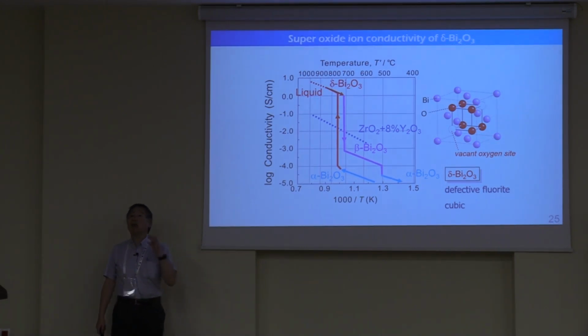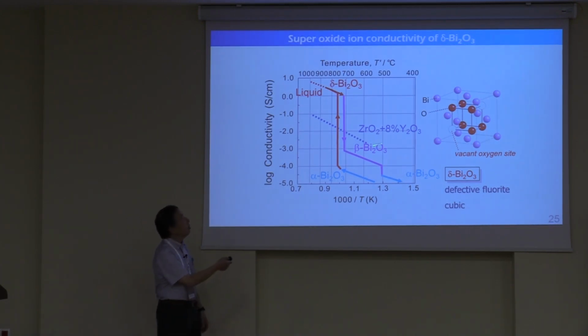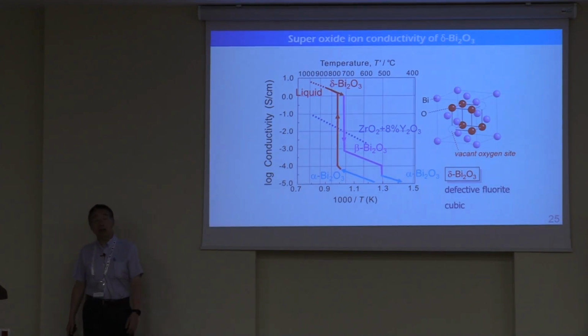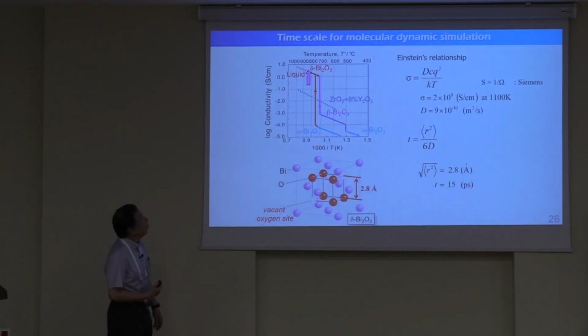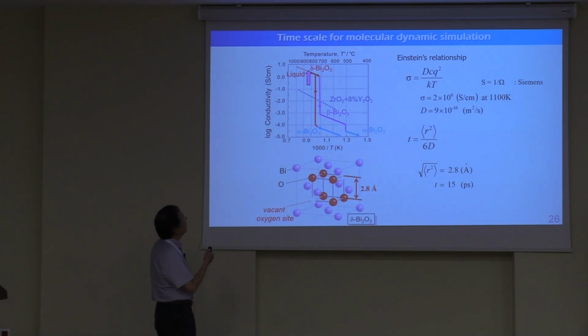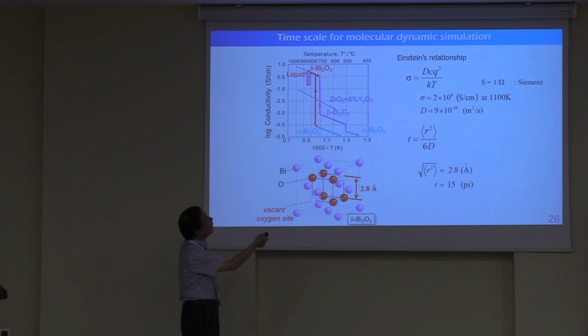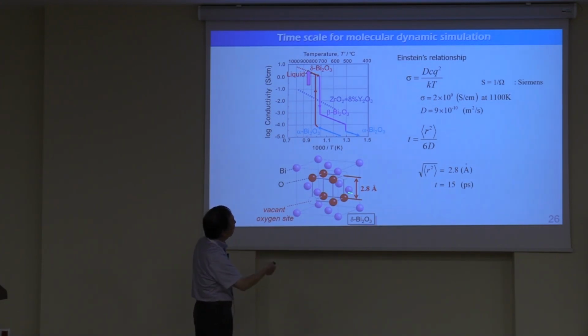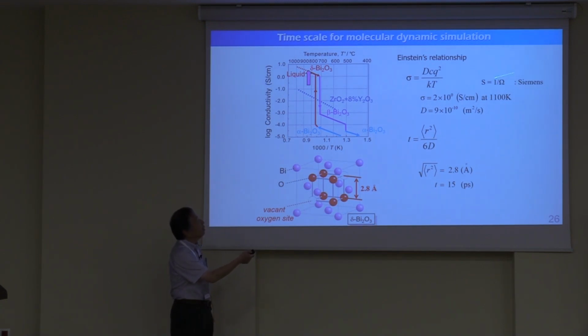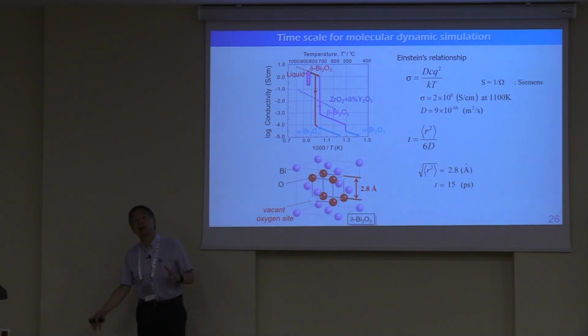Quite often for the oxide ion fuel cell, zirconia doped with yttrium is used for the ionic conductor. But the bismuth oxide has two orders of magnitude higher ionic conductivity. So we simulated this one by first principles molecular dynamics. By a simple estimate of the conductivity using the Einstein relationship with this conductivity and also the lattice parameter or bond length here, we can estimate the time required for this jump is something like 15 picoseconds at 1100 Kelvin. So of course we need a longer calculation than 15 picoseconds.